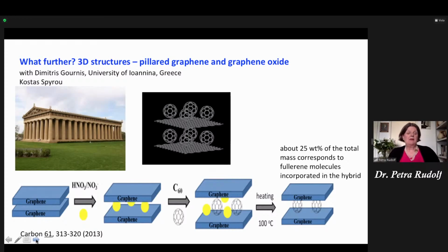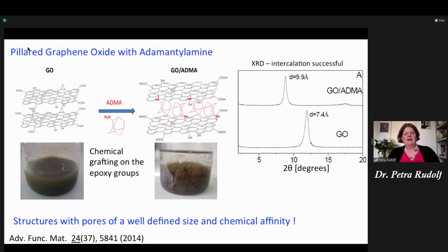It's not particularly good at hydrogen storage, but it was a very nice adventure to start to work on pillared structures. And since then, we have done a lot of pillared structures together, but we work very often with graphene oxide, because the nice thing with graphene oxide is that when you bring in a molecule, this molecule can then bind to the functional groups on the graphene oxide, where you have OH groups, all kinds of functional groups on the sheets. And the NH2 of this molecule here binds. And in this way, you get a permanent pillar in here.